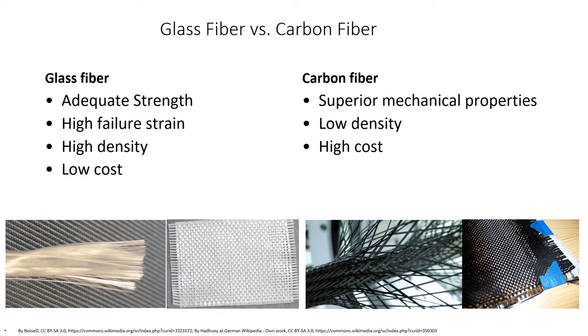The stiffness of the composite is defined by the stiffness of the fiber and their volume content. Typically, E-glass fibers are used as the main reinforcement in the composites. The glass-epoxy composites for wind turbine blades contain up to 75% glass by weight, which increases the stiffness, tensile and compression strength. A promising composite material is glass fiber with modified compositions like S-glass, R-glass, etc.